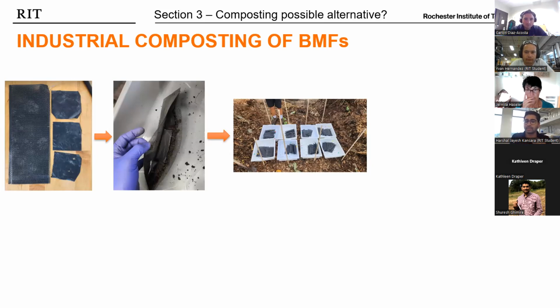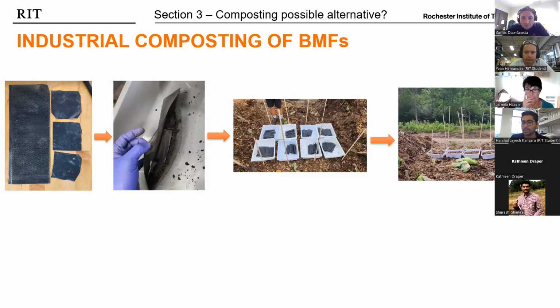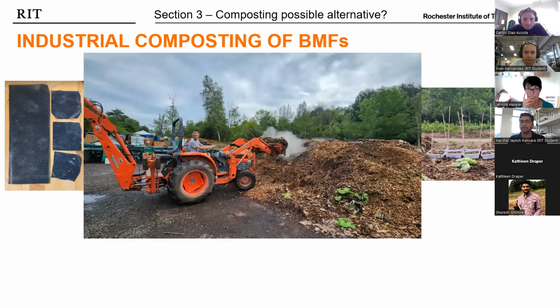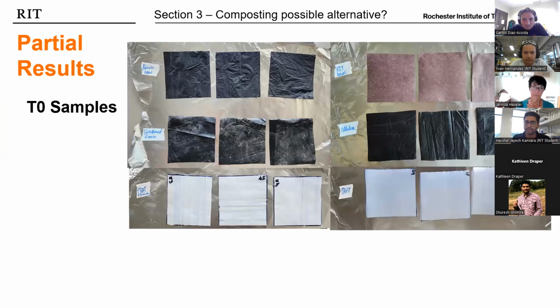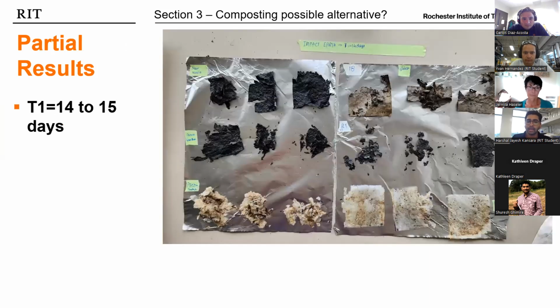Once we stuff the compost inside in such a way, we pile up these bins with the rest of the composting material on top to bury them completely inside these industrial composts. Once that is done, we retrieve the samples every 10 to 15 days. These are some of the T0 samples, so this is how the samples look initially. And after 14 to 15 days, you can see how much more the samples are broken down or fragmented.